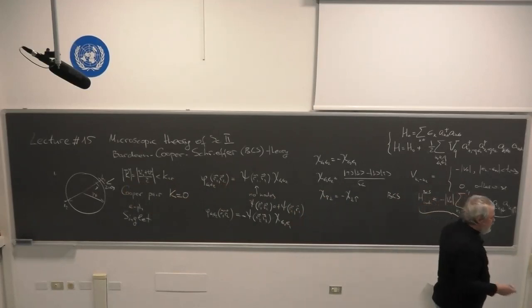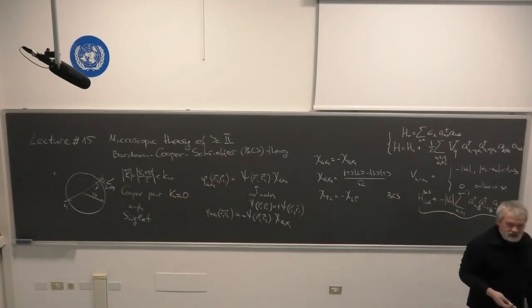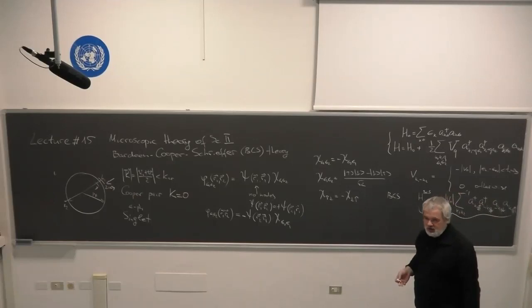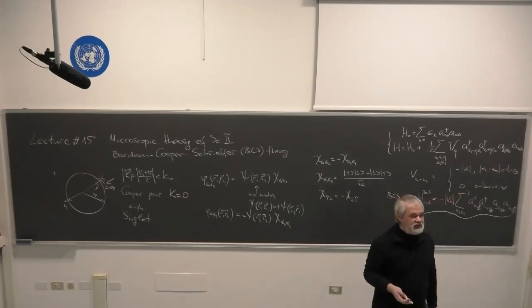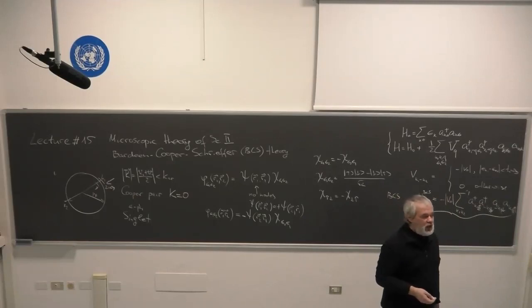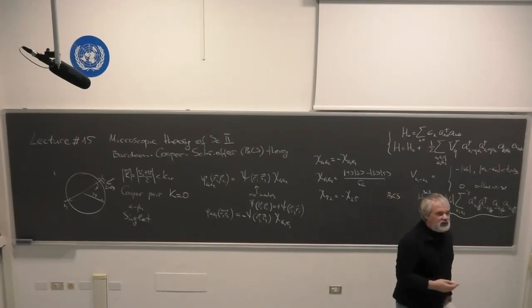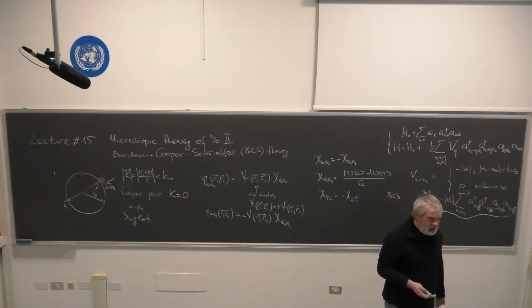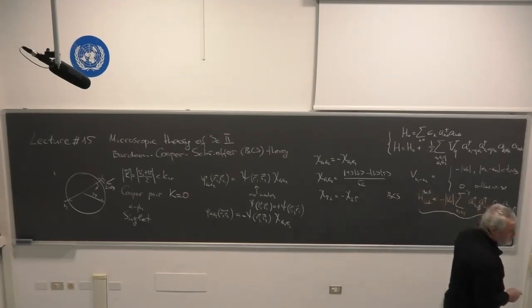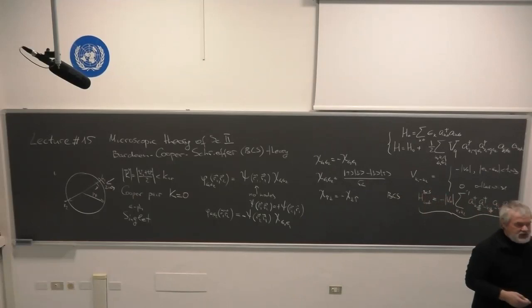You may ask me why phonons come to the mind of theorists, why people started to look at phonons. There was actually experimental indication that the critical temperature of known superconductors depends on the isotope you use. Namely, you can use systems with different isotopes. Sometimes you have the option to take a material with a different isotopic content, and people realized that the critical temperature is inversely proportional to the square root of the mass of the isotope.